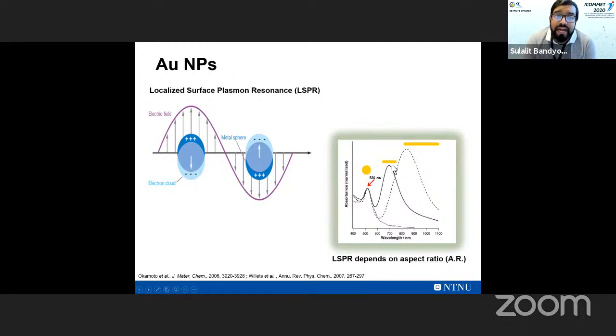The moment you have anisotropic rods, which means you have two axes, a long longitudinal axis and a short transverse axis, you get two peaks, one around 520 nanometer, the other one at a longer wavelength. And then if you further increase the aspect ratio, you shift this to longer wavelength. And this is interesting for different kinds of applications.